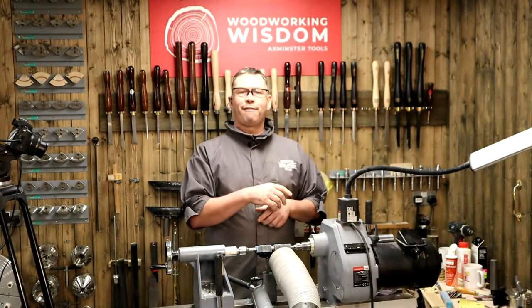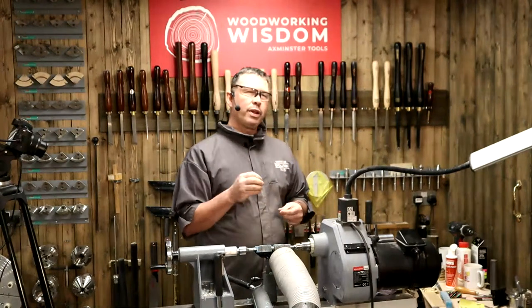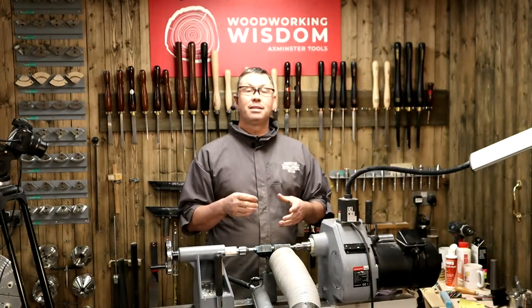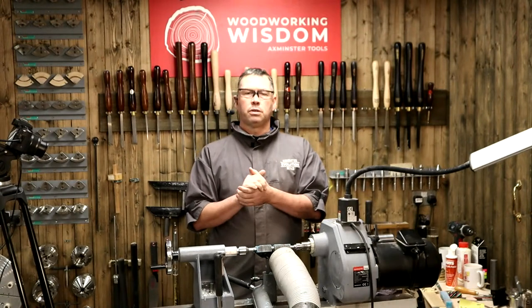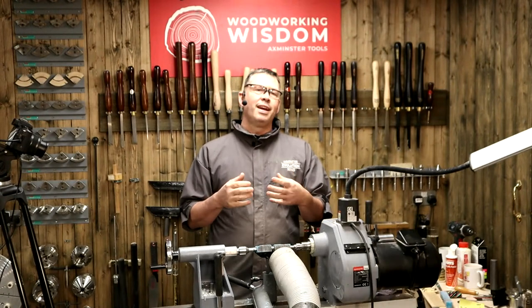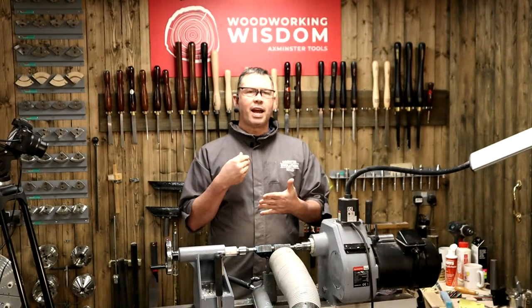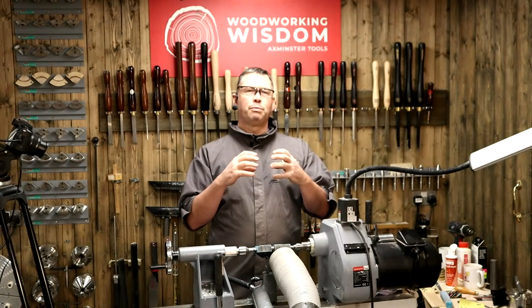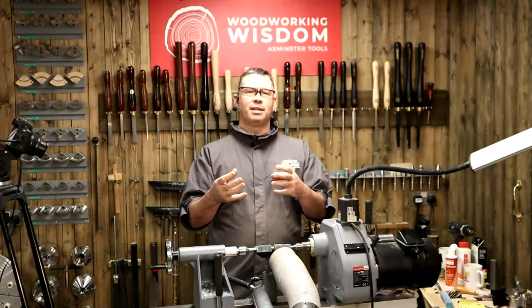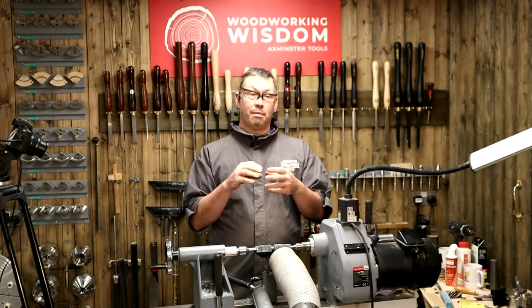Let's talk about the failures first before I go any further and actually start the lathe up. I wanted to do some polymer clay, because it was a question of yours a few weeks ago, I think, to turn some polymer clay. I haven't done a lot of it. I haven't overbaked it. What I've done is I had the heat of the oven up far too hot, and so I almost burnt the outside. My kitchen last night was full of smoke. I burnt the outside, but the inside stayed soft.